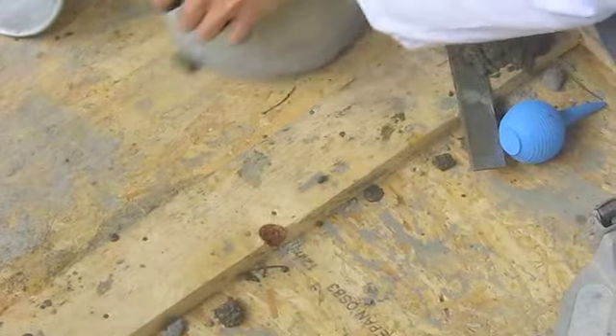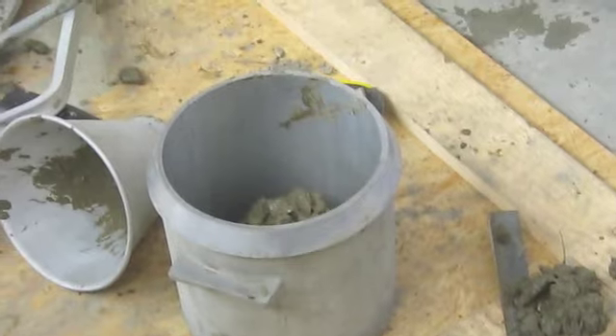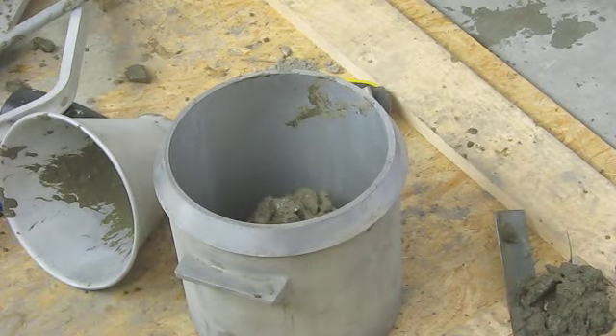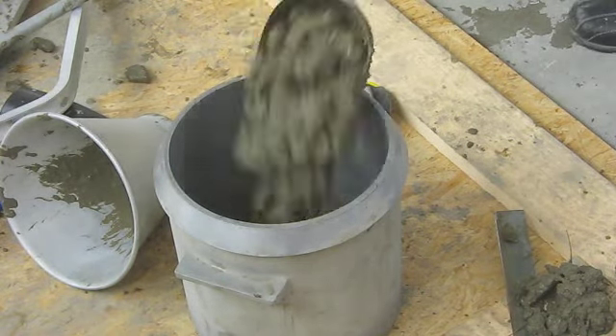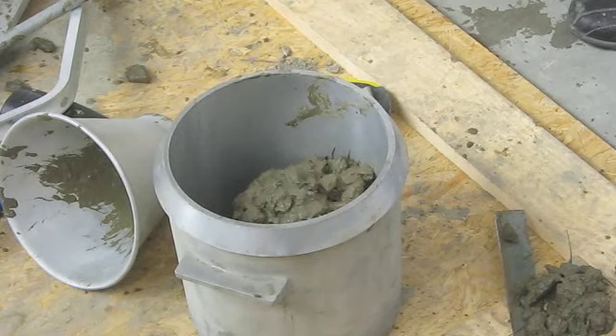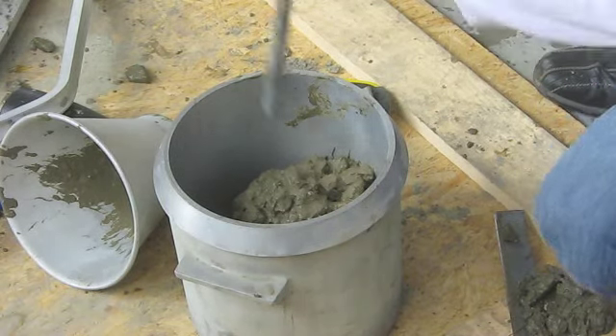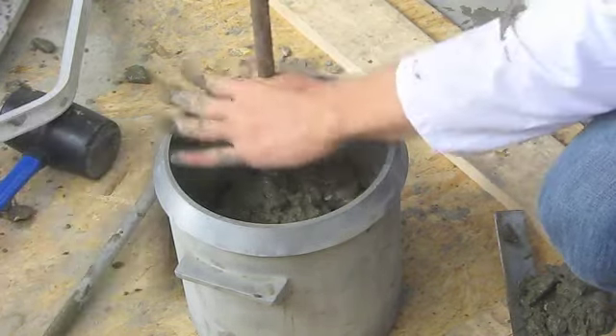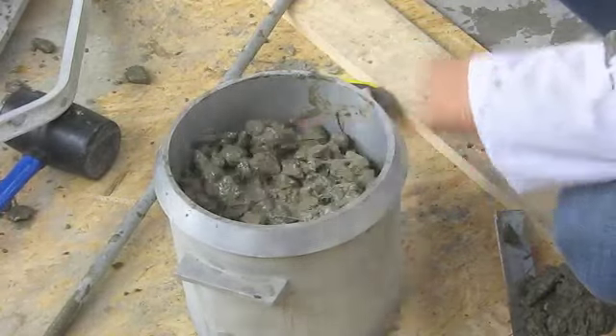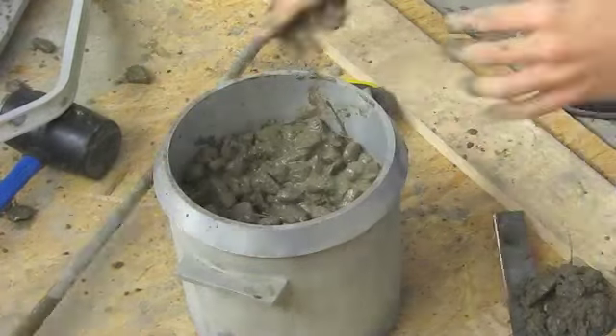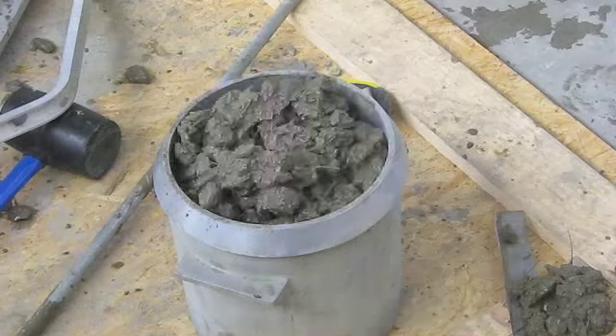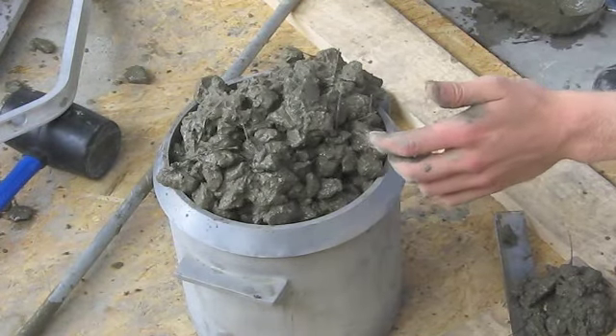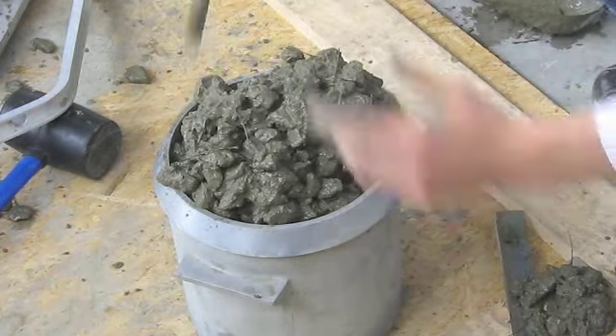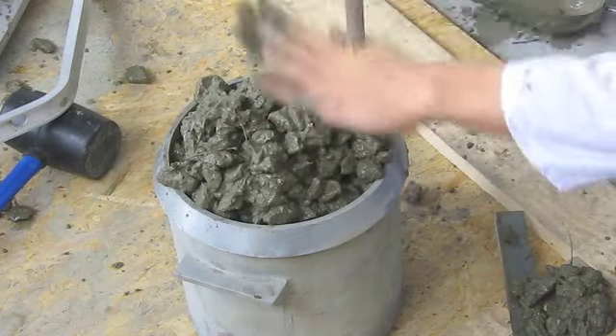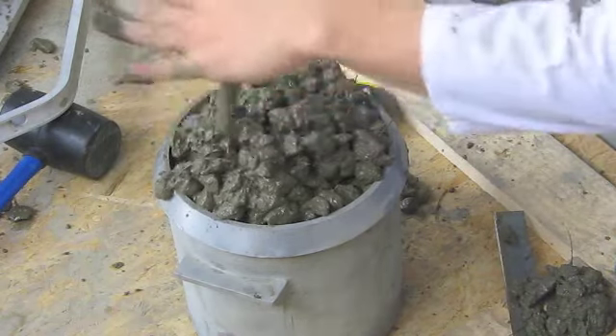For the air content test, again, you want to fill the measure a third full with your concrete mix, and just like the slump test, use a large tamping rod and tamp 25 times in succession. Complete this for each lift. When you get to the top, you want to make sure that you overfill. Each time you want to make sure that you're only penetrating 1 inch into the layer below.